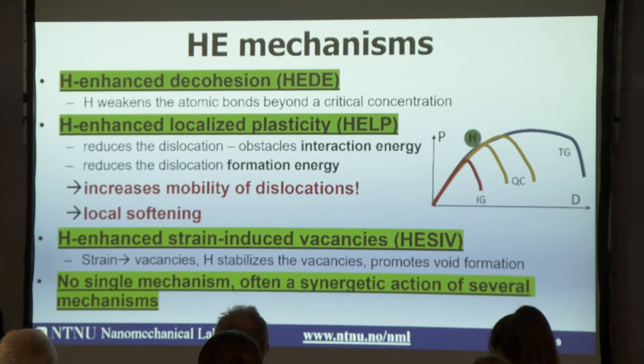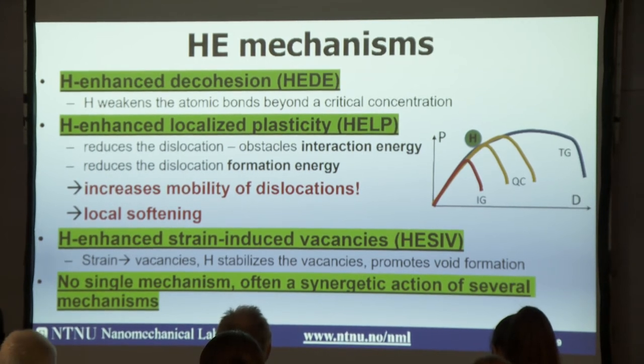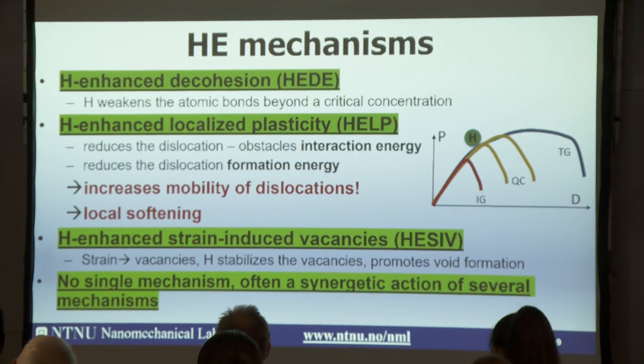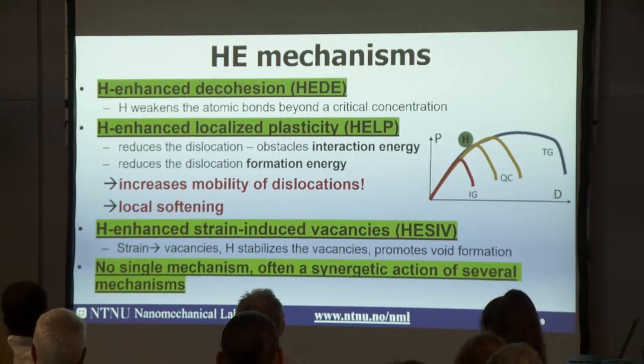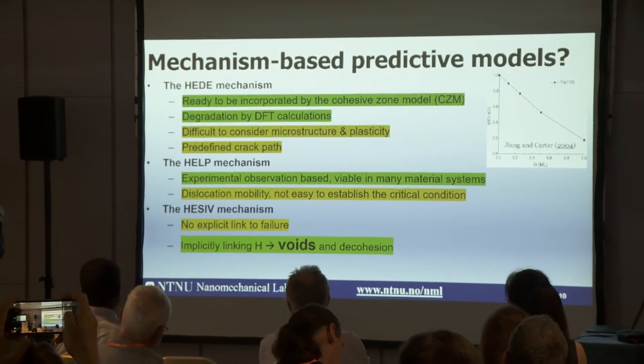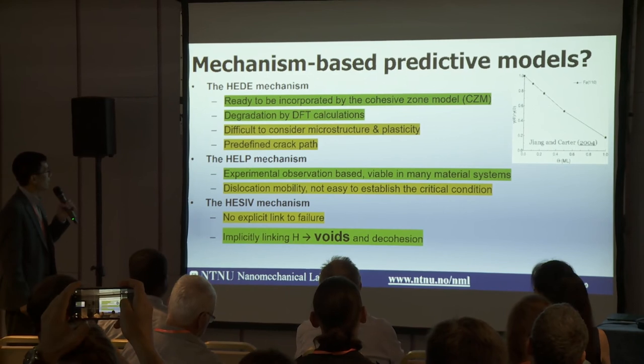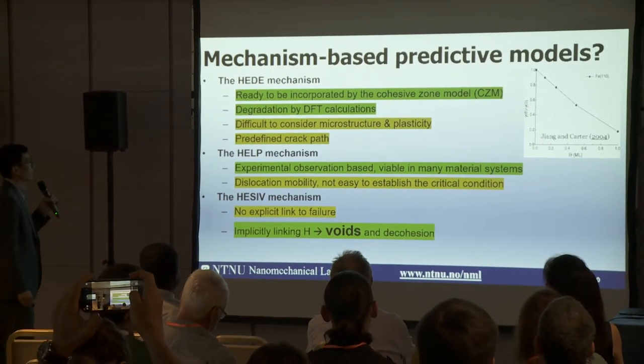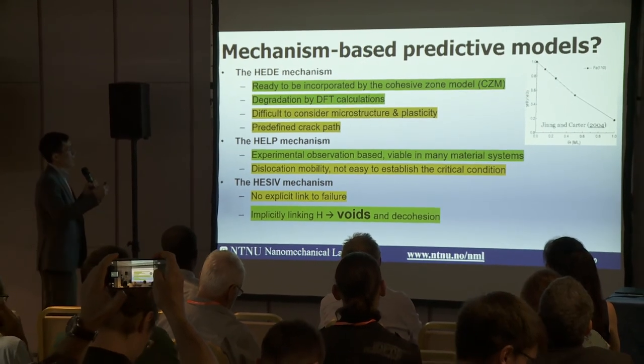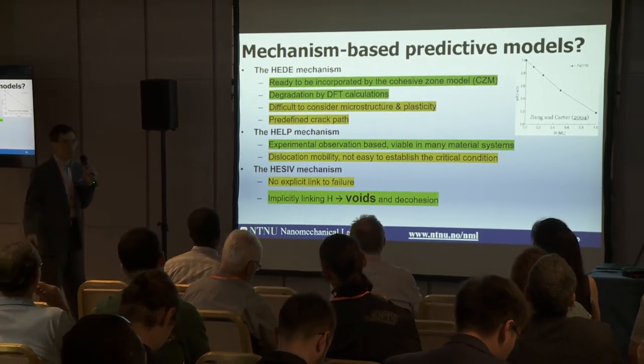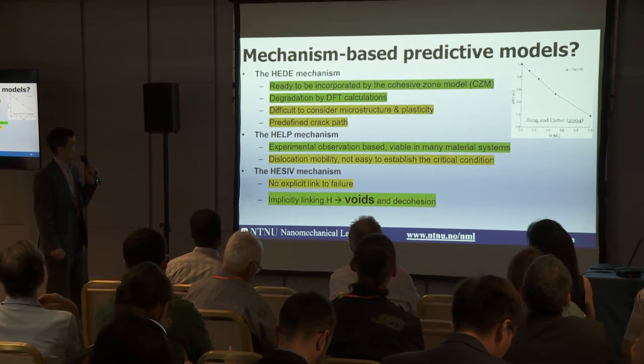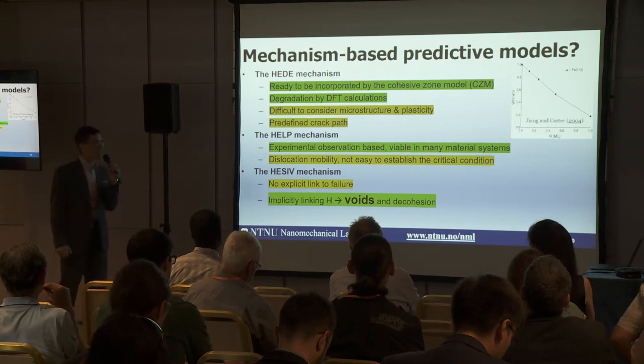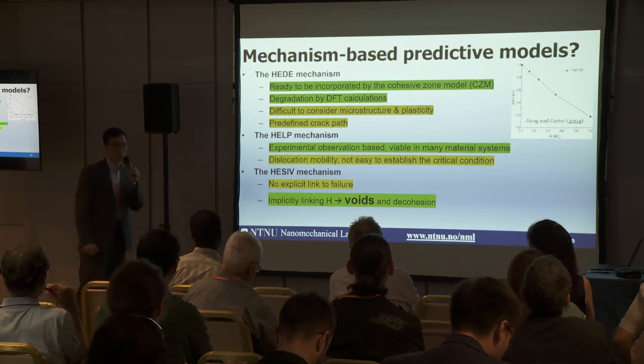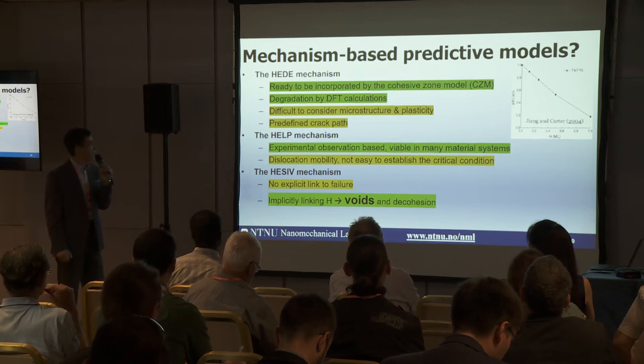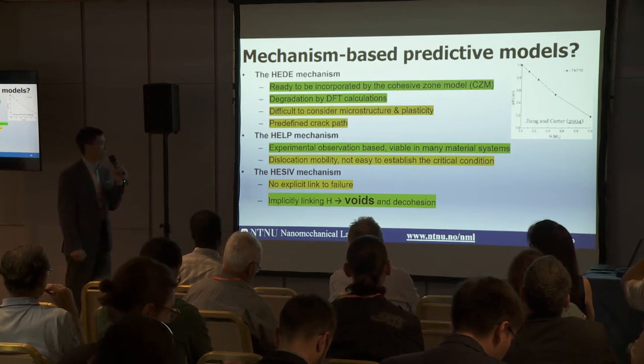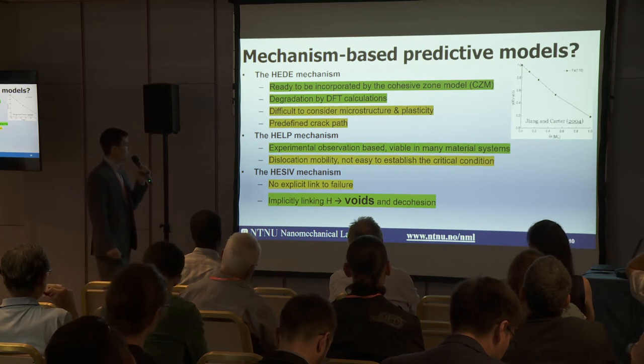You may ask, we have so many mechanisms. Is it possible to develop mechanism-based predictive models? The answer is yes and no. If we go through the three mechanisms, the HEDE mechanism is ready to be incorporated by the cohesive zone model. The degradation can be calculated by DFT, density functional theory. However, it's difficult to consider the microstructure and the plasticity in the HEDE mechanism.